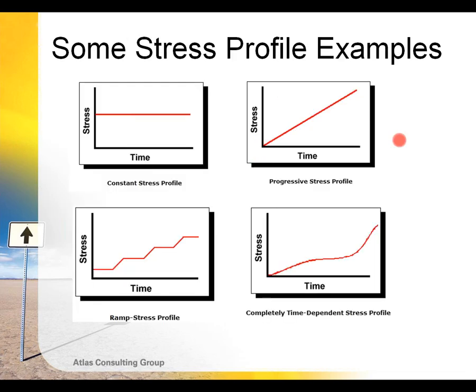Some of the different things that we can do in terms of how we deliver our stresses, for example, we can deliver our stresses steady state. And again, steady state conditions virtually never happen out of doors, and oftentimes don't even happen indoors. So very often steady state tests don't always tell us very much or aren't very predictive or correlate well with field performance, such as steady state salt fog corrosion tests are notoriously poor at predicting coating or metal corrosion in the field. We can have ramping type tests where we increase the ramps of the stress levels, either linearly or stepwise, or with some other type of a curve, and this delivers not only thermal or mechanical stresses, but can also, in some cases, deliver changes in chemical stresses that are more realistic in terms of the service environment.